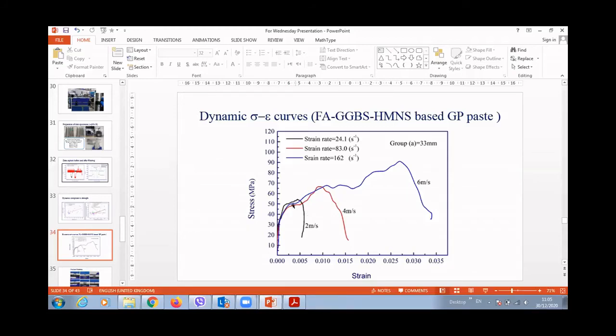it has a slow improvement, which is very close to the linear stage, a slow improvement with the increase of the strain, representing the hardening stage. And then finally, at the top here, the stress reached the ultimate value and dropped quickly or harshly. And this represents the compressive failure of the samples.